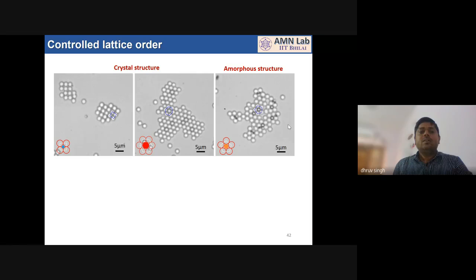So the lattice order of the structures here is mainly decided by the shape of the starting unit cells. Square or hexagonal unit cells can always be fit in a regular pattern. But if you have a pentagonal unit cell, then you cannot fit it into an ordered pattern or close packed patterns. Then you end up with the amorphous state. So controlling the lattice order is also an interesting thing, because the people who grow epitaxies or crystalline materials know how difficult it is to go from one to the other, or to define the lattice order.